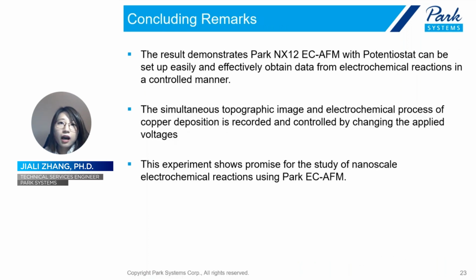So with that, I want to get to our concluding remarks. In this study, we made an electrochemical system in AFM with CV measurements for in situ observation of the electrochemical reaction. We observed copper deposition and dissolution during CV measurements with EC-AFM, and also obtained in situ images of the surface morphology. This AFM showed the in situ morphology changes during electrodissolution of copper.